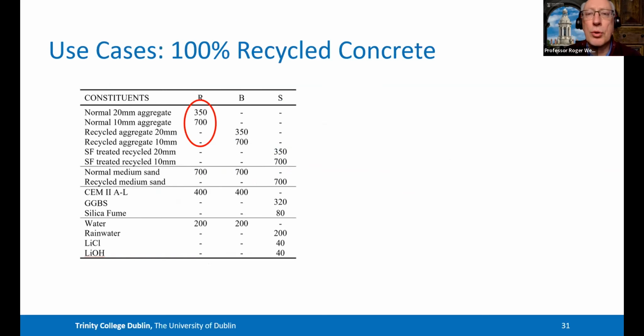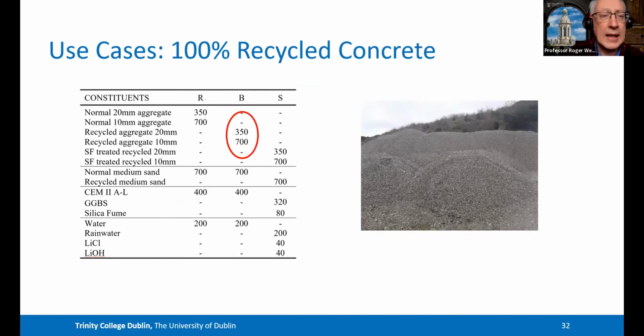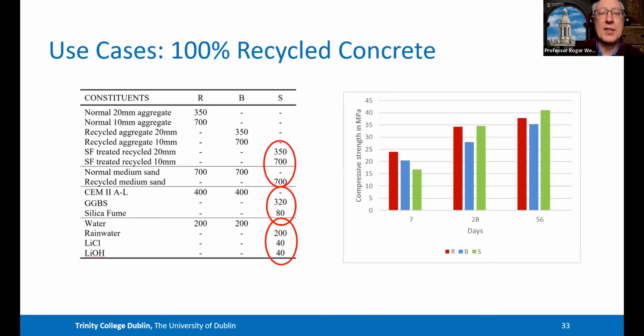And then finally, last case, I just want to say that we've been involved over a number of years in making concrete which is 100% recycled. So again, if you look at the typical quantities of stone, I've highlighted them there in red. Here's the recycled one, which we would have seen before. This is 100% recycled aggregate using 20 and 10 millimeters. And then this is the one we want to look at, where we deliberately use silica fume to pre-treat the recycled aggregate so we don't have such a water loss problem or a workability problem. We've used recycled medium sand from a quarry. We've used a filler as well.